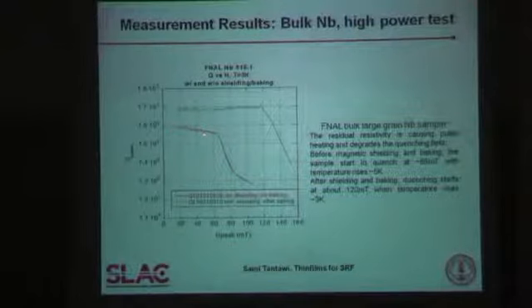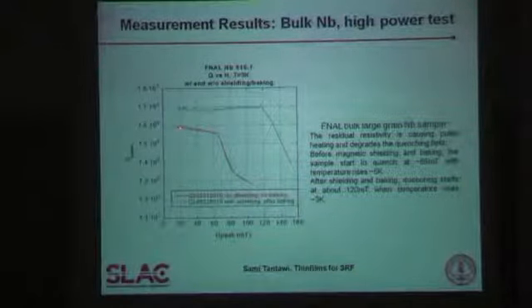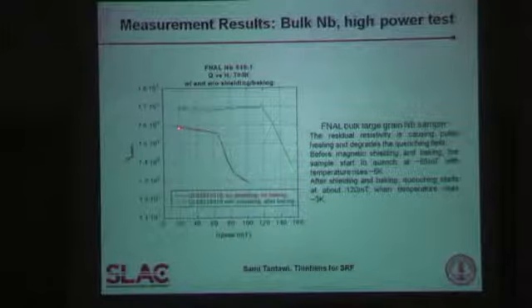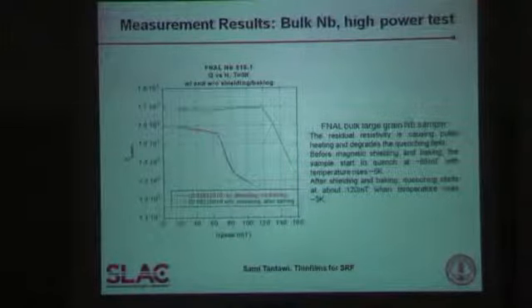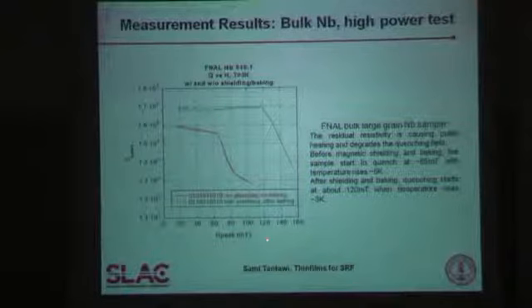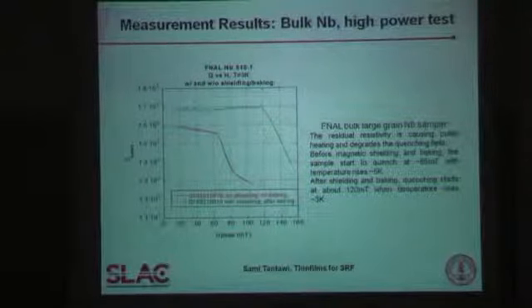After we applied magnetic shielding, two things happened immediately. Before magnetic shielding the quenching limit was close to about 65 to 70 millitesla with that slope, and that slope was clearly caused simply by heating the sample temperature. After magnetic shielding the slope almost disappeared completely and we are now quenching at around 120 millitesla.